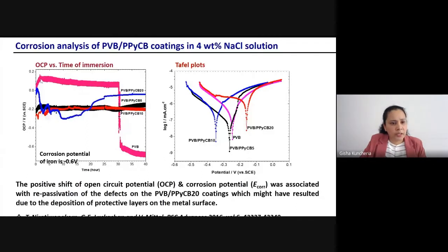If you look here, the y-axis is the open circuit potential and the x-axis is the time of immersion. On this diagram, you can see how the polymer is giving the protection. The corrosion potential of iron is minus 0.6 volt. This is fixed. But by application of the polymer, the potential is moved to nearly 0.1 volt. That means this PVB coating is giving very good protection.